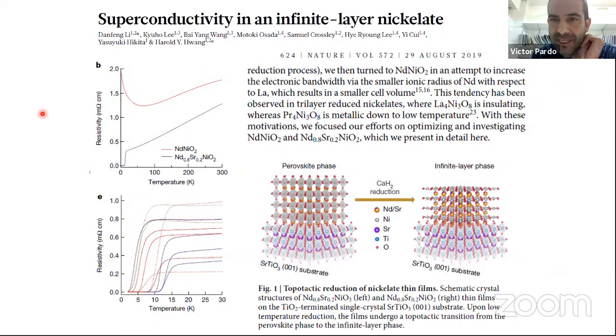So now we come to 2019, and in 2019, this paper by Harold Hwang's group appeared, where they finally found superconductivity in one of these nickelates, in particular doping neodymium nickel O2 with strontium. The reason why they said they introduced neodymium instead of lanthanum in the nickelate is to basically mimic our idea. We had seen that introducing praseodymium instead of lanthanum brings about metallicity because of the smaller size of the praseodymium, and they said that they tried to follow our idea of using neodymium to make it more metallic than lanthanum. And well, they succeeded in getting a superconductor, and this was a great excitement for all of us working in this field for many years already.